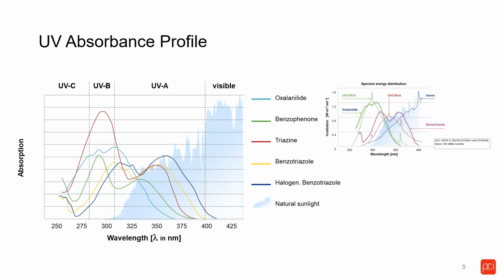However, important to keep in mind, the energy carried by a photon of natural sunlight is inversely proportional to the wavelength, which means those photons at 310, 320 nanometers will carry much higher energy and consequently will have a much higher negative or degradation effect on the coating applications. And that explains why the UVB absorption is critical for a UVA, and the triazine having the highest one will very much dictate what happens in a natural weathering test.